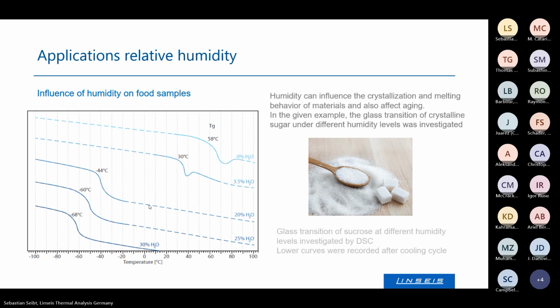So we tested the melting and we tested the crystallization by DSC. You see it easily as a peak - this peak here is the melt. On the other hand, you see phase transition down here at negative temperature range.